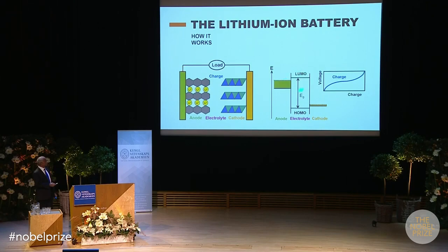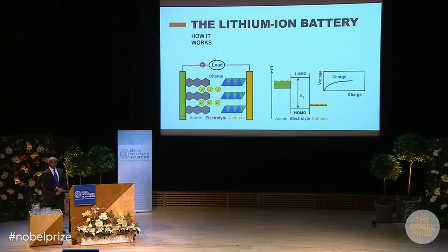On the other hand, supposing the LUMO lies below this level, then when we charge, we will put the electron from here to the LUMO rather than here, and that can lead to the leakage of electrons internally and short circuit. Finally, you can notice during charge, the voltage slightly slopes upwards because the energy difference between these two is increasing. During discharge, exactly the opposite happens because the energy difference between these two is decreasing.